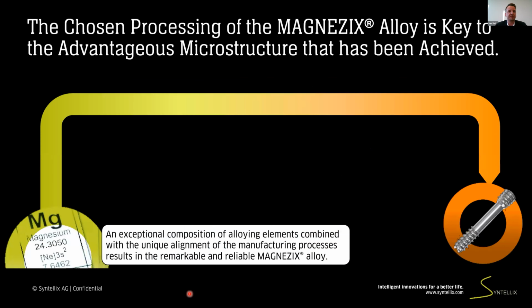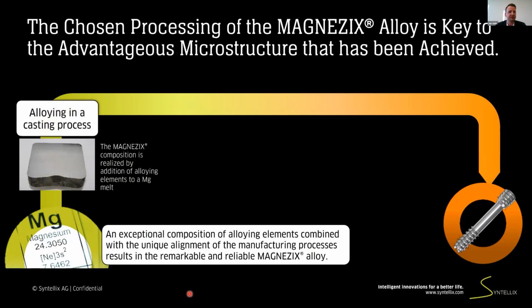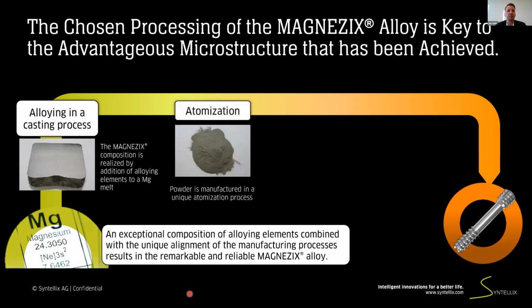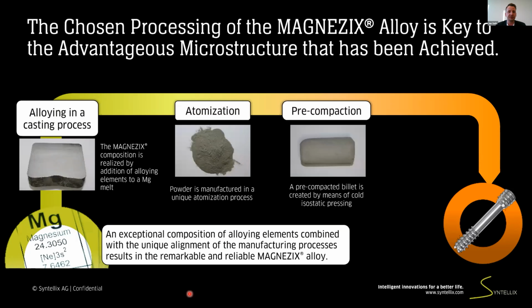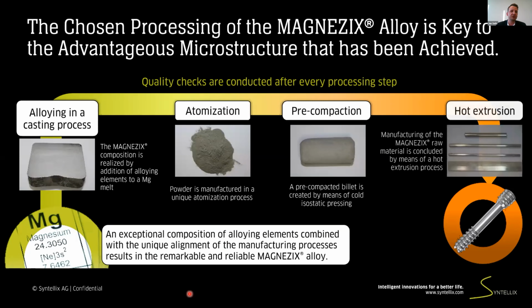The Magnesium alloy is manufactured by means of the following processes. The composition is prepared in a casting process by adding the required amounts of alloying elements to the Mg melt. Subsequently, atomization is carried out in order to achieve small powder particles, which are then pre-compacted in a cold isostatic pressing process. Extrusion will then result in the final raw material rods, which possess a very fine-grained microstructure. These rods will then be used in a CNC turning process to manufacture the final one-of-its-kind devices.